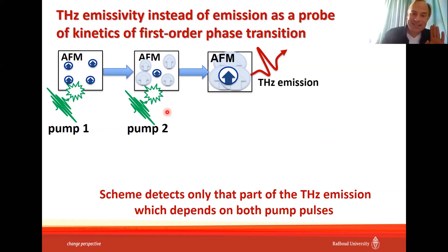We detect THz emission from pump two, but at the repetition rate of pump one. Basically, we detect THz emission from pump two, which was affected by pump one. In this way, we exclude nuclei which were already in the medium before pump one from consideration. So the scheme detects only that part of the THz emission which depends on both pump pulses.